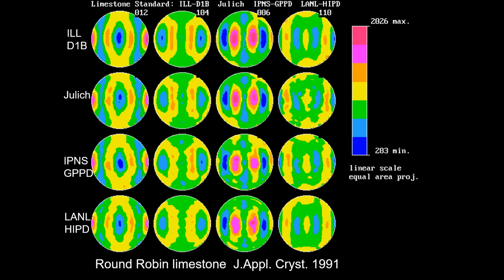And what was amazing for me is that the results were for all very similar, which is different for, for example, a pole figure goniometer with X-rays, where you have a lot of problems with absorption and also with corrections for tilt, which have to be taken into account.